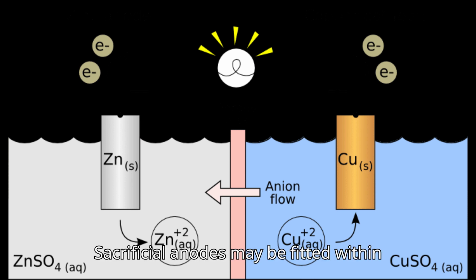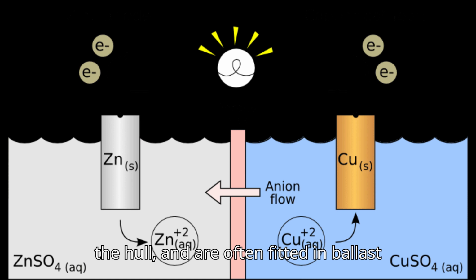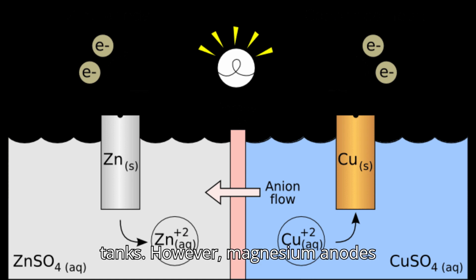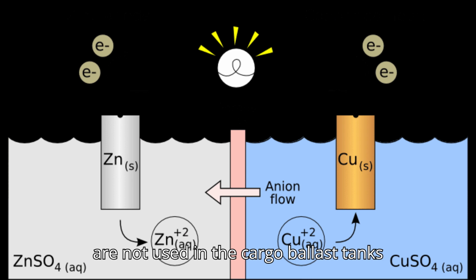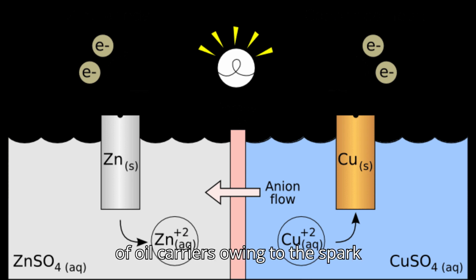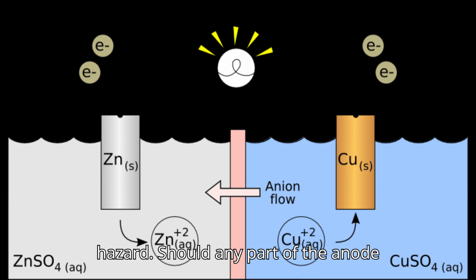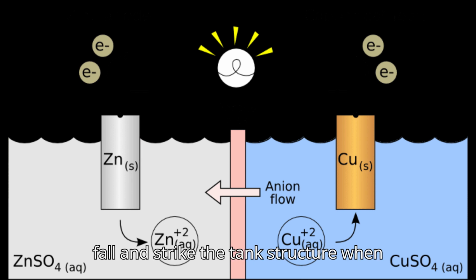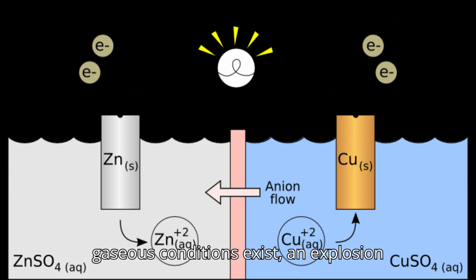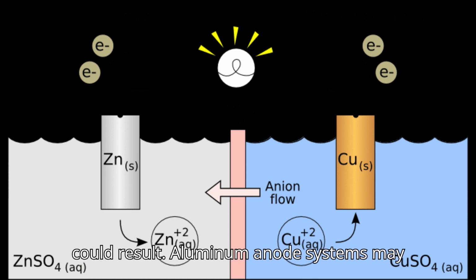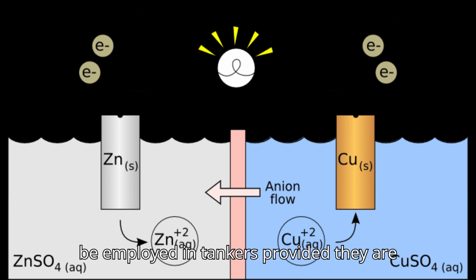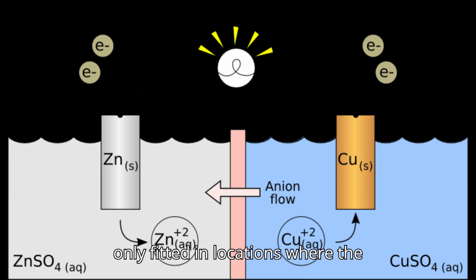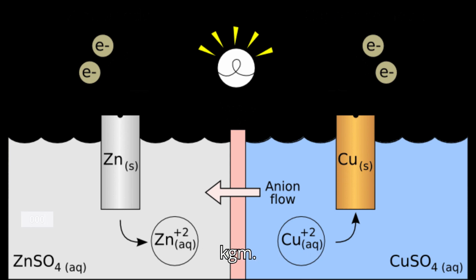Sacrificial anodes may be fitted within the hull and are often fitted in ballast tanks. However, magnesium anodes are not used in the cargo ballast tanks of oil carriers owing to the spark hazard. Should any part of the anode fall and strike the tank structure when gaseous conditions exist, an explosion could result. Aluminum anode systems may be employed in tankers provided they are only fitted in locations where the potential energy is less than 28 kgm.